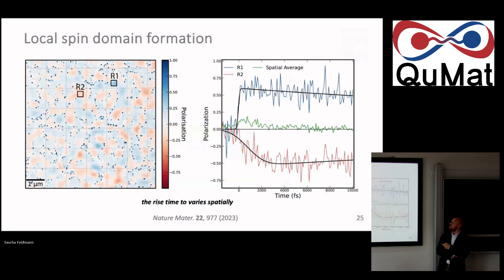So if you look at such maps now of these different polarization domains, positive and negative ones, you will find that the kinetics associated with every one of these pixels is also vastly different. And you see that the positively polarized domains actually have prompt kinetics, and negatively polarized domains have delayed ones.